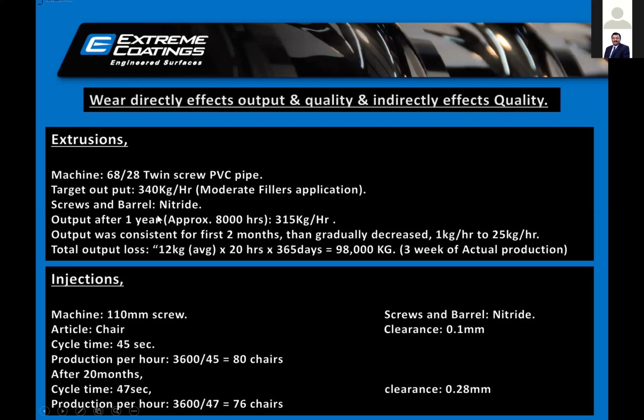After 1 year, approximately 8,000 hours of production, the same machine was giving an output of 315 kg per hour. On average, when we calculated the output loss into the hours into 365 days, the production loss of that particular machine was 98,000 kg, which was actually 3 weeks of actual production of that machine. So almost 21 days in a year your machine was not functioning. That was the kind of loss that processor was making.